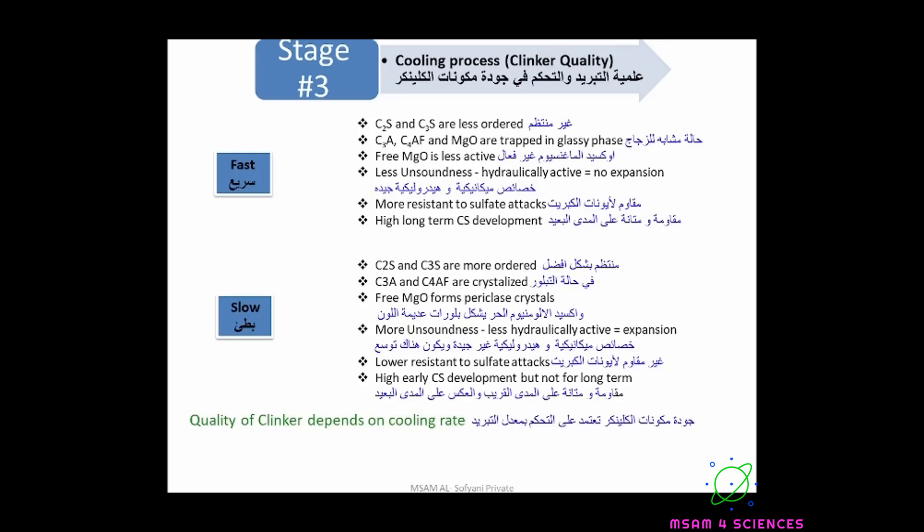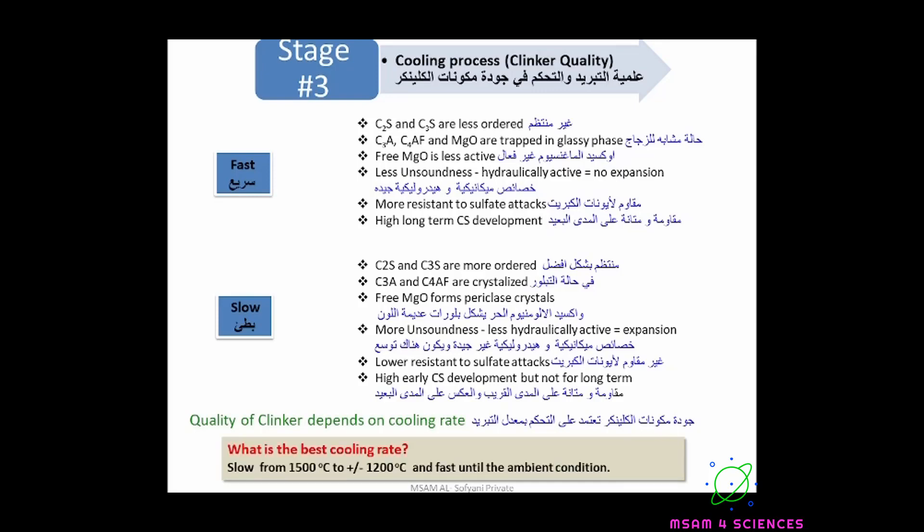So here we can see clearly that the cooling rate determines the quality of clinker. The best approach is to go slow from 1500 degrees Celsius down to 1200 degrees Celsius, then fast cool down to ambient conditions.